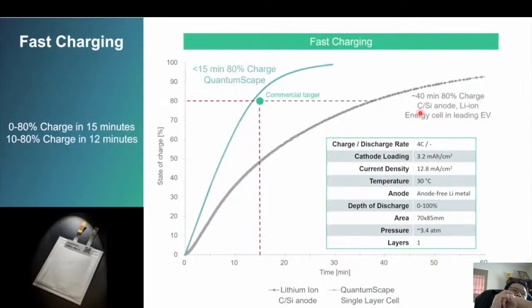So then fast charge is another really key requirement, we think. So how do our cells do in fast charge? So this, in blue here, is data that we collected on cells in our lab showing fast charge capability. So the y-axis is the state of charge over time on the x-axis. So we did here a 4C charge rate, and you can see the cell charging up quite quickly. It beats this target we have set for ourselves of 80% in 15 minutes.